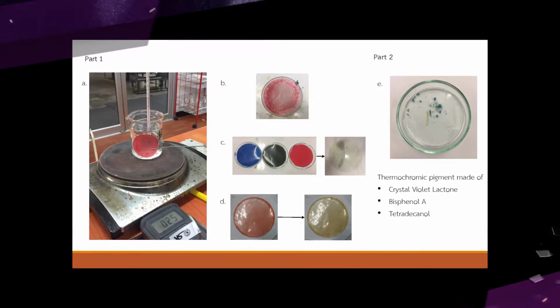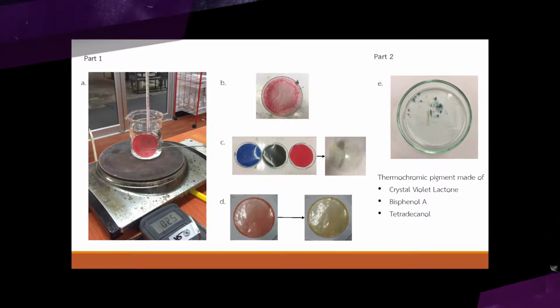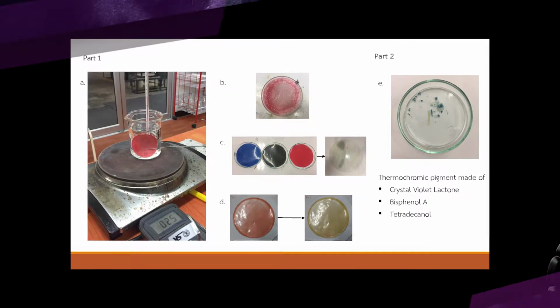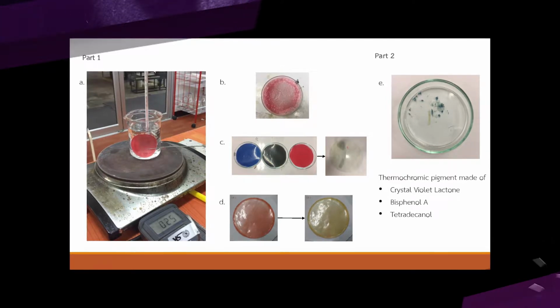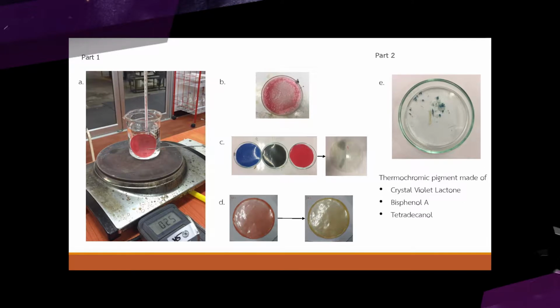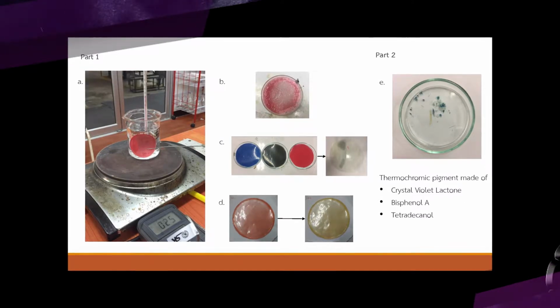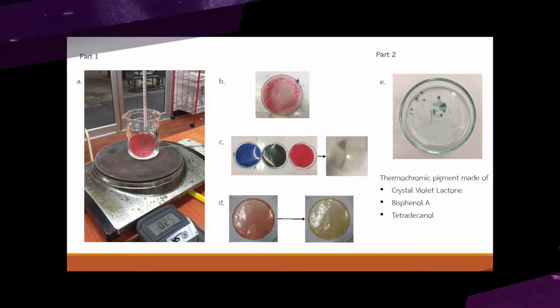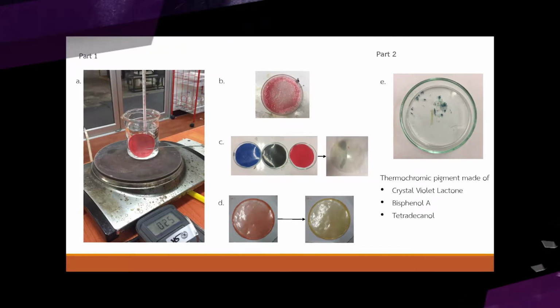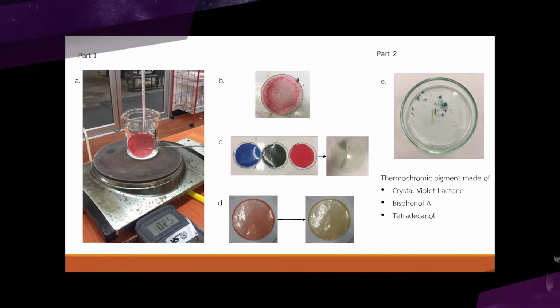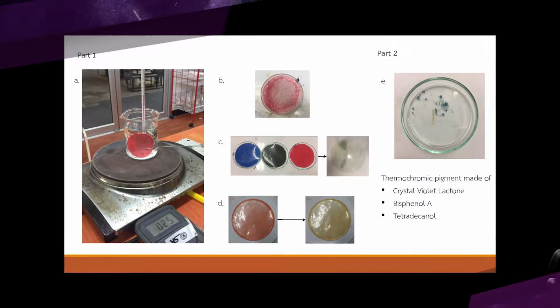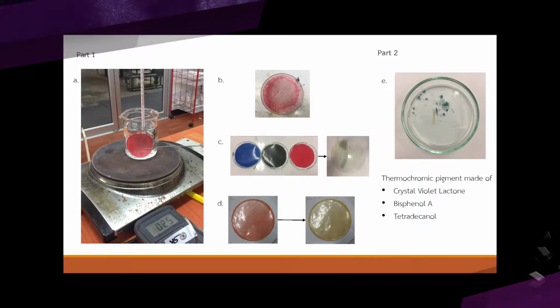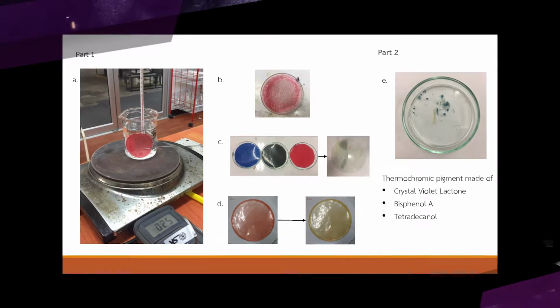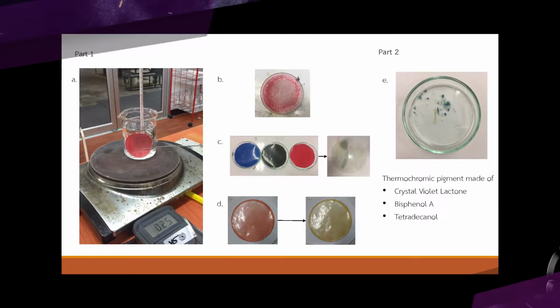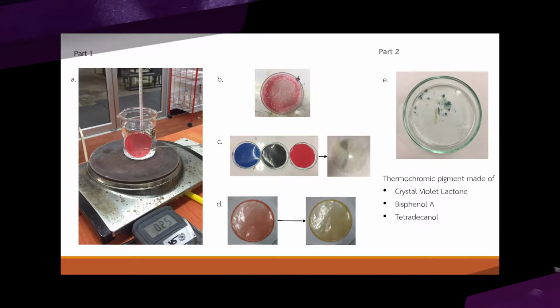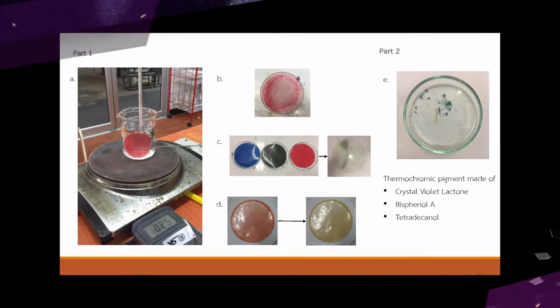And for polyvinyl alcohol, the color of the film permanently disappears when the heating rate is above 2.36 degrees Celsius per minute, as shown in figure C. And for natural rubber, the color of the film stops reversing when the heating rate is higher than 1.7 degrees Celsius per minute, as shown in figure D. So it can be concluded that heating rate is the factor that affects the reversibility of the thermochromic system. Each type of polymer has a different limit of heating rate due to differences in thermal conductivity.